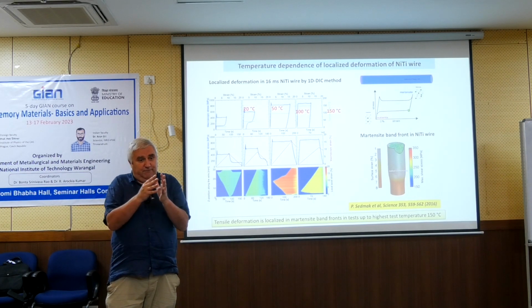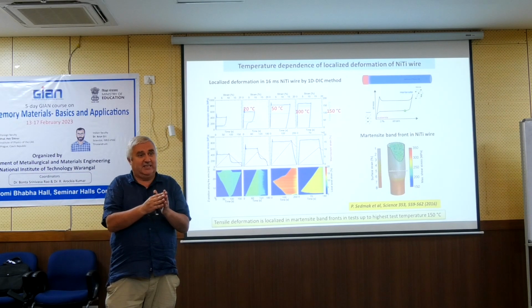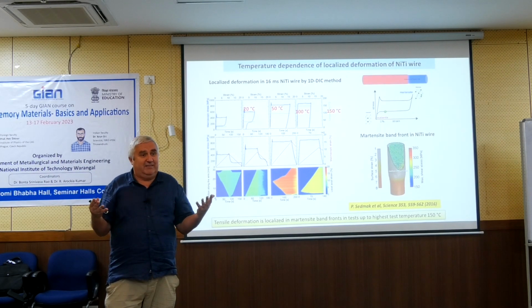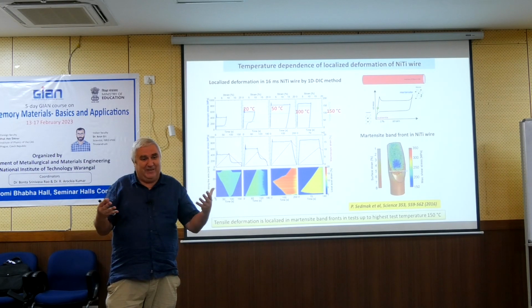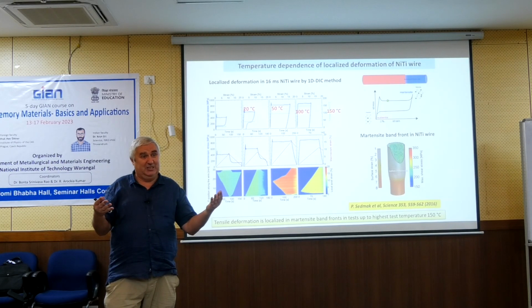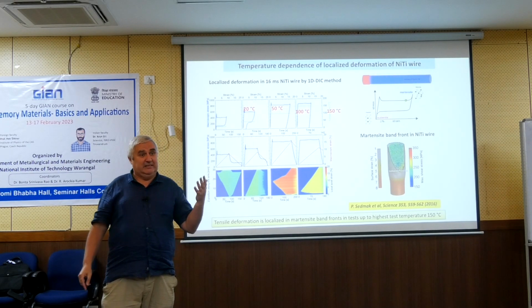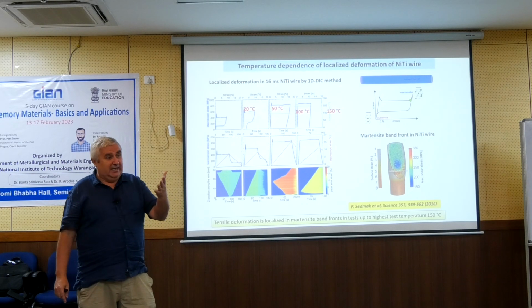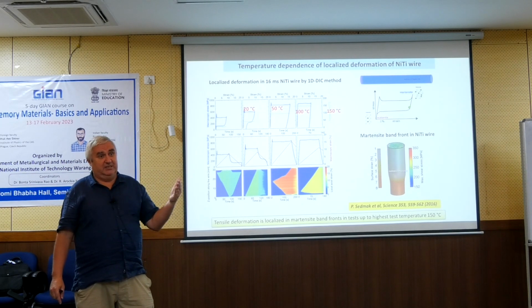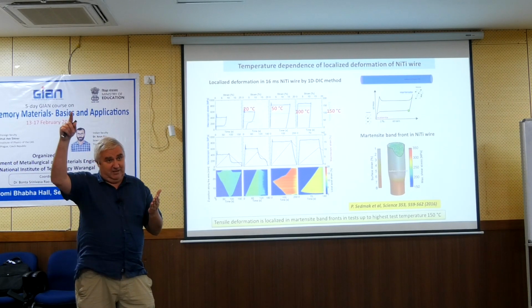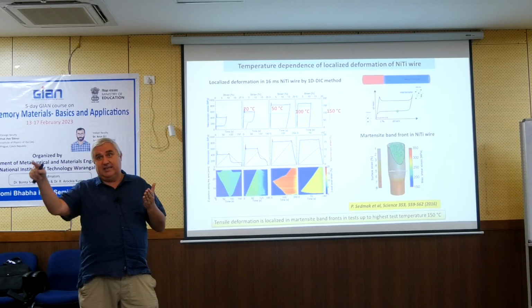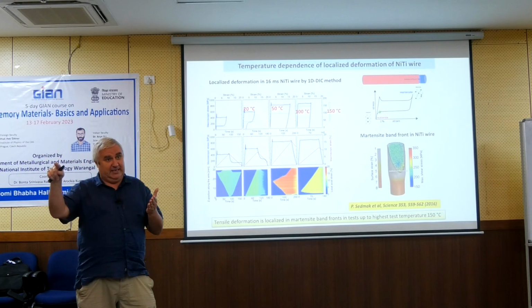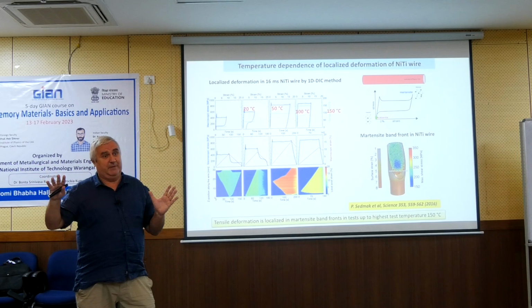But for your question, why there is a hysteresis, this is a very basic question. I can only answer that it is always here because energy is dissipated during the Martensitic transformation. During elastic deformation, no energy is dissipated, so even if you have nonlinear elasticity, you would have the behavior like that, because the energy is not dissipated.